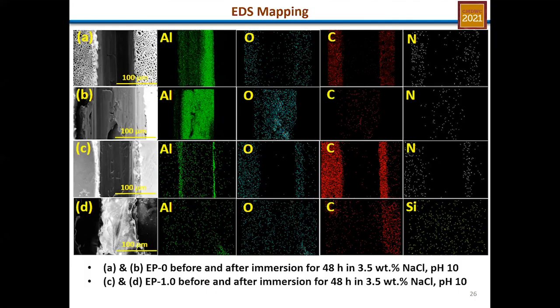Now, in order to validate this, we carried out EDS mapping. From the EDS mapping, you can see that A is that of the substrate that is unloaded, and D is that of the substrate that was loaded and was healed after the 48 hours it was immersed at pH 10. And when we analyzed just the scratch plane and the healing film that was formed, we realized that we had more distributions of carbon, silicon and oxygen, which came from both the healing agents and some influence from the nanocomposite, of course. But if you look carefully at this EDS mapping, we found out that we had better inhibition, and the presence of these materials confirmed that what we had in the scratch plane was the passive film that had been formed from the diffusion of the healing agents to the scratch plane.